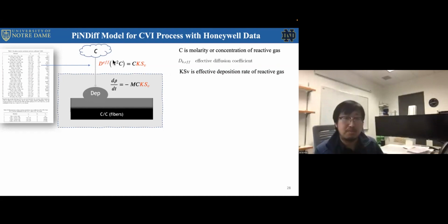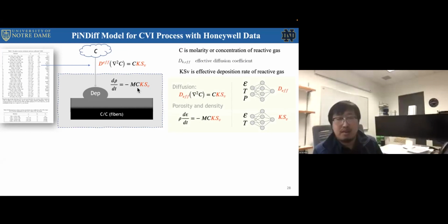And we definitely have this diffusion term, but what is the effective diffusion rate, which is a spatial temporal field, is not known. Okay, so we have the neural model to handle this, and the C is the molarity or the concentration of the reactive gas, and here we just treat this as an effective gas. So we don't separate out the different species. And this KSV is the effective deposition rate of this reactive gas. So the whole process is deposition and diffusion. Okay, so there's a lot of things we don't know, the effective deposition rate and also the effective diffusion coefficient.